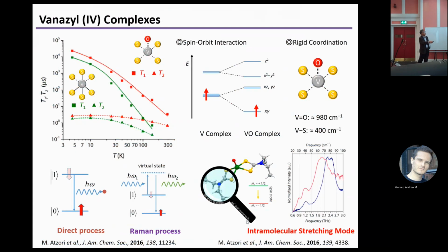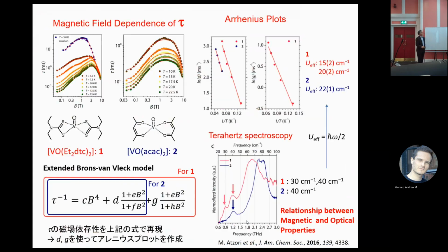You can see one compound shows 2 peaks, the other compound shows 1 peak. So this is an intramolecular stretching mode detected in the terahertz region. We correlate between magnetic properties and optical properties such as the terahertz region. Then this is another compound, oxyvanadium compound 1 and oxyvanadium acac compound 2. This is the magnetic field dependence of relaxation. This compound has 2 relaxation times from the Arrhenius plot, and this has 1 relaxation time.